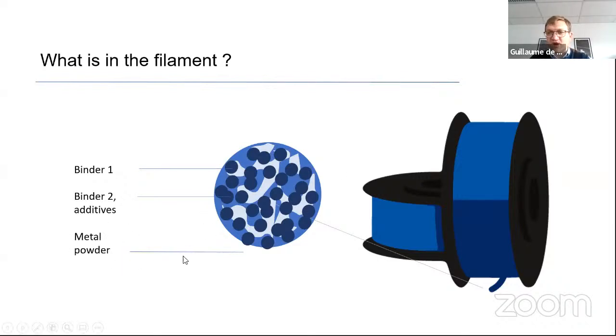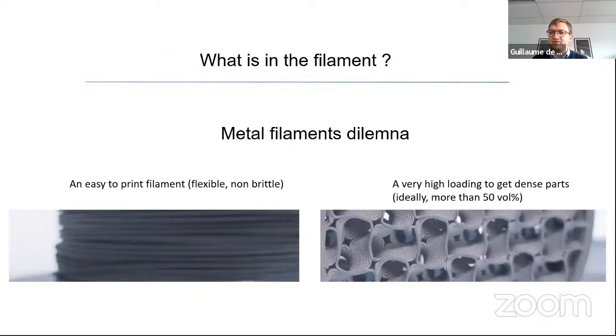There's this question of how much powder you have inside a material. When you're developing a filament, there's usually a dilemma between you want a filament that's as easy to print as possible. That means flexible, non-brittle, with reasonable printing temperature, all of these things. But on the other side, you also want to have a very high loading of metal or ceramic powder. If you don't have enough powder in your material, it won't be possible to get to a dense material afterwards. And usually what we say is we need around 50 volume% of the mix that should be metal powder. That's a critical point here. We're talking about 50 volume%.